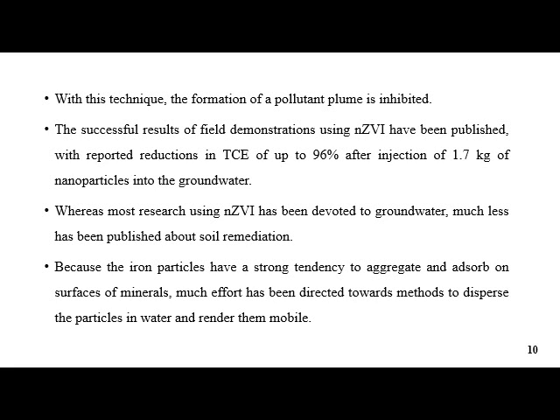Nanoscale zero valent iron particles have been used to immobilize chromium in chromium ore processing residue. Because the iron particles have a strong tendency to aggregate and adsorb onto mineral surfaces, much effort has been directed toward methods to disperse the particles in water. Approaches include water-soluble starch as a stabilizer, hydrophilic carbon and polyacrylic acid delivery vehicles, and modified cellulose — sodium carboxymethyl cellulose (CMC) — to form highly dispersed nZVI. Several polymers have also been tested and found effective.